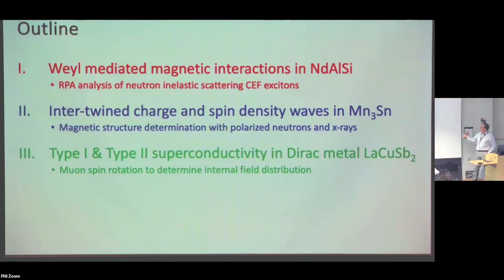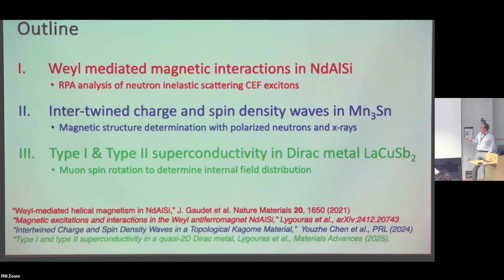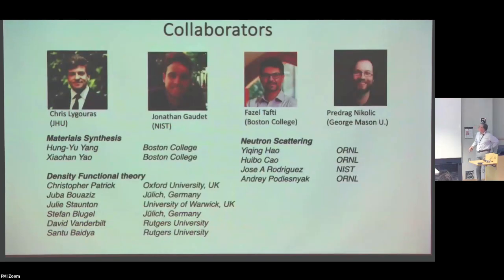The interesting thing about this material is that it actually has type 1 superconductivity for one field direction along the uniaxial direction, and it has type 2 superconductivity in the other direction. So this is kind of an unusual aspect of this. And all of these things are published, either actually published or in arXiv articles. Actually, this one I think is now. This one has appeared in print, but it's also available in arXiv. Okay, so the first part is going to be about neodymium aluminum silicon, and these are the collaborators.